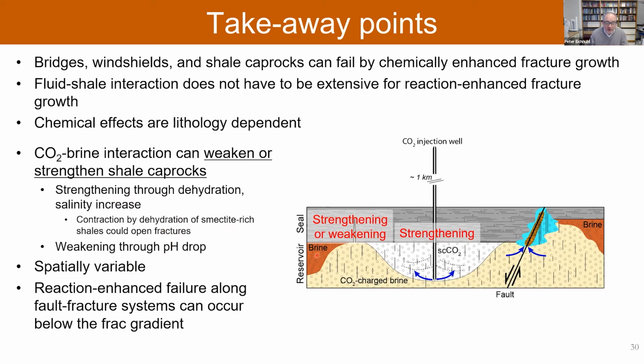All this would be spatially variable because it depends on where the supercritical CO2 is, and where the CO2-charged brine is. So this could be spatially variable, and over time, as the CO2 dissolves in the brine and you push out the CO2 plume, this behavior could change over time. And as I said, faults may be the host of where those fractures occur, but ultimately it's fracture growth that controls the leakage behavior.